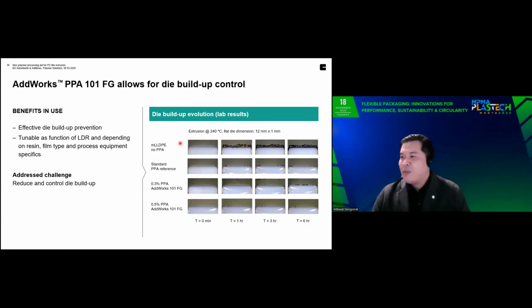In terms of dye build-up, we conducted this test using the metallocene LLDPE resin. After running from 1 hour up to 6 hours, the dye build-up is there - you can see the black color substance at the die. After comparing with the standard PFAS at 500 ppm, you can see the improvement in terms of dye build-up.